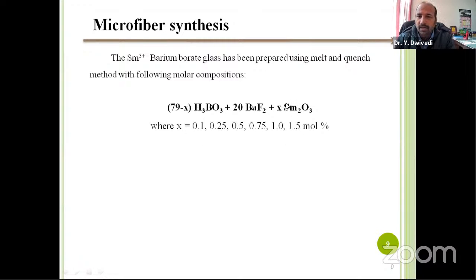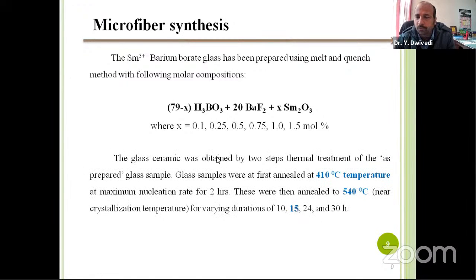I use samarium ion as a probe ion to see any change in microstructures. Different concentrations can be used, starting from 0.1 to more than 1.5 mole percent.